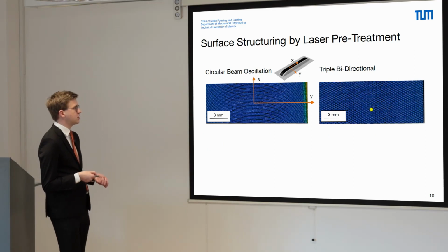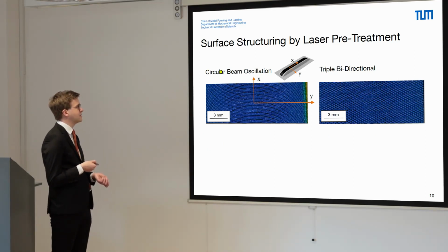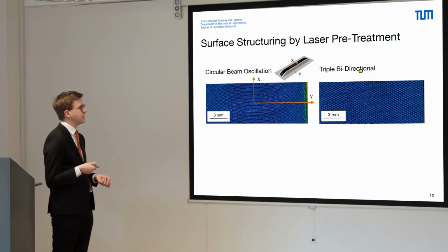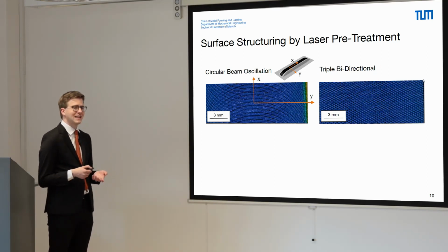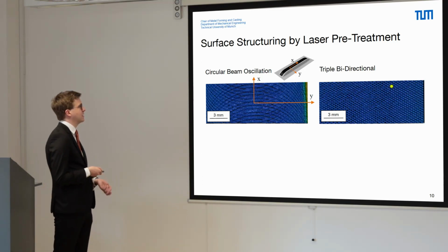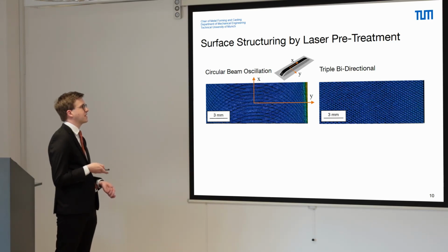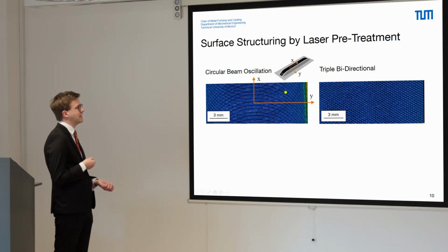In comparison, here we show two macroscopic images of the resulting circular beam oscillation and triple bidirectional strategy, and one can see at first glance that it's more of a regular structure. Here the beads of the laser structuring process using circular beam oscillation, here more of a triangular-like structure for the triple bidirectional structure. And the circular beam oscillation shows more of an anisotropic roughness enhancement in the direction of the bead axis.